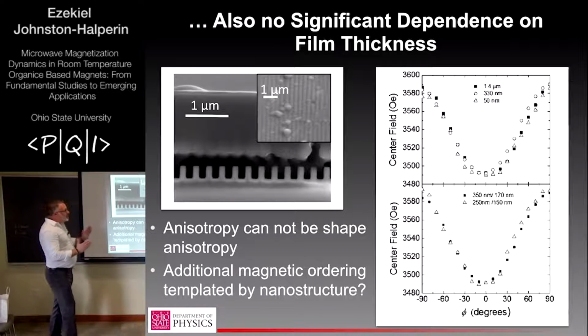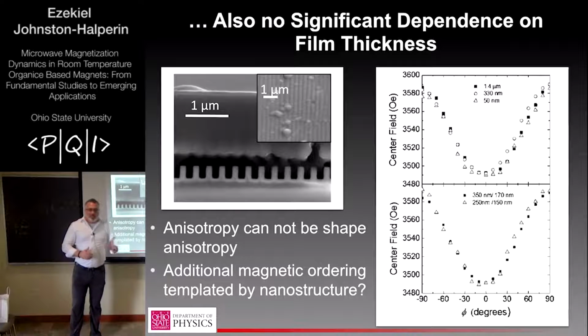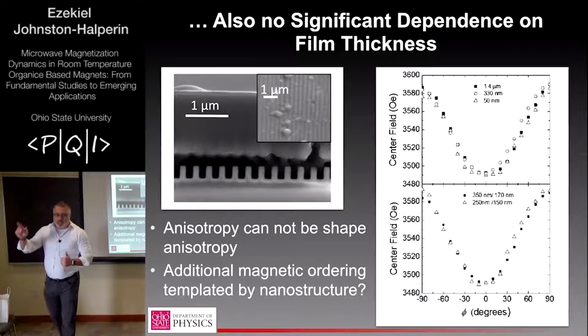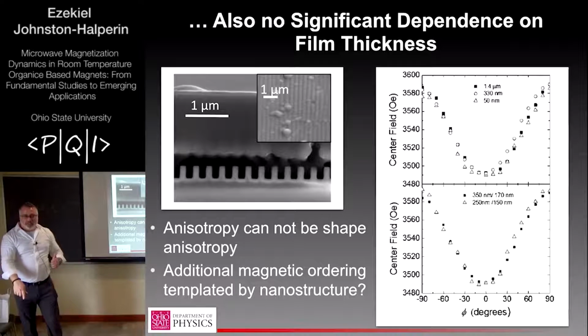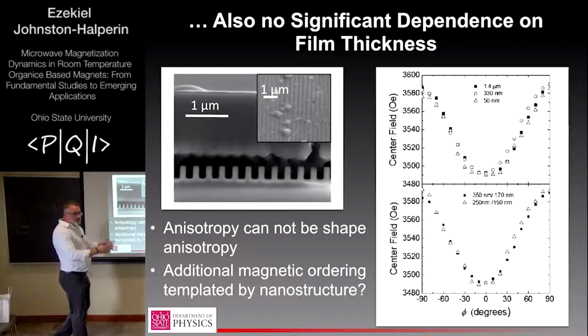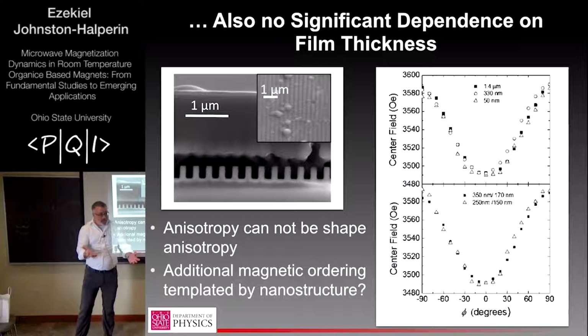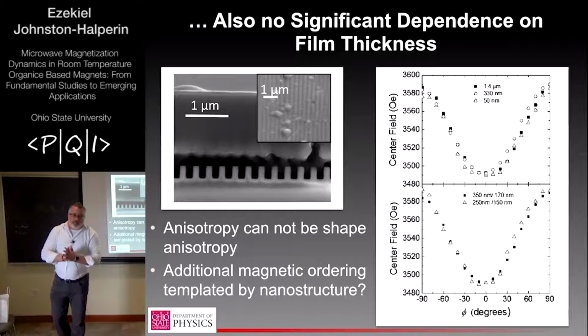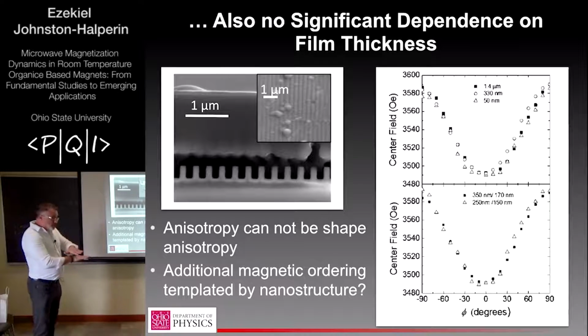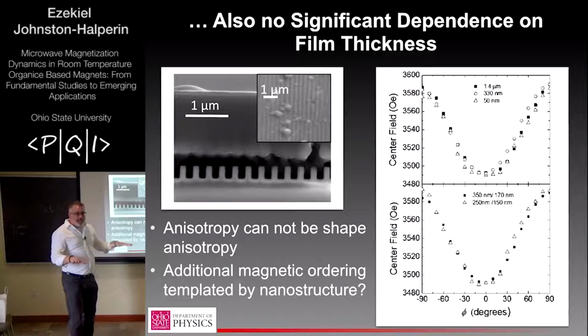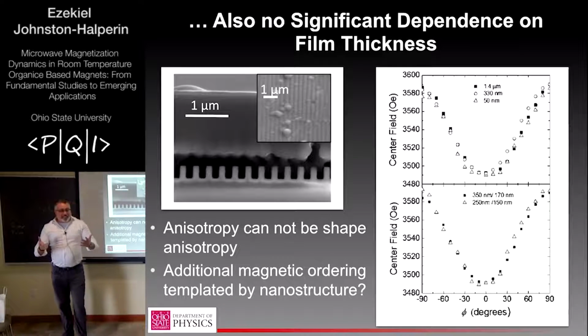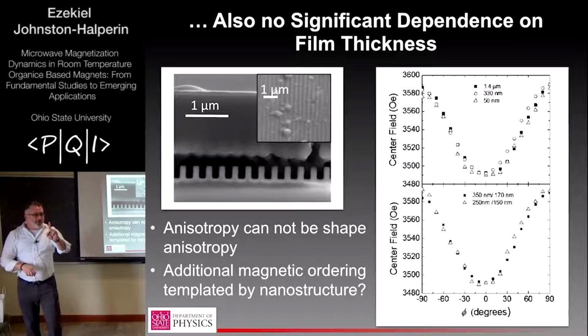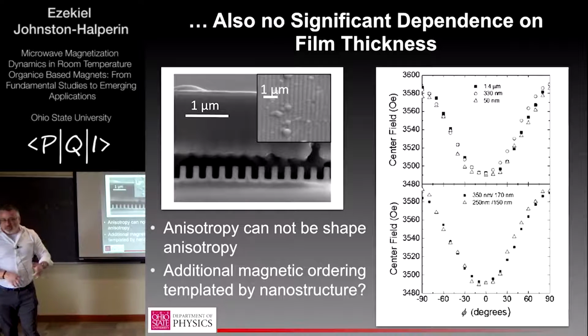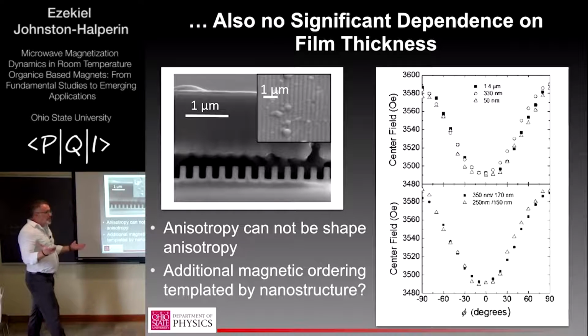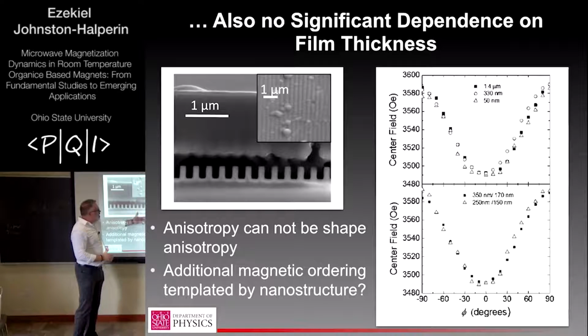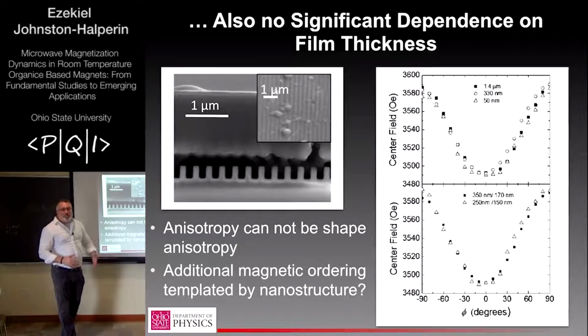And so retroactively, coming back to the data I showed you at the very beginning of the talk, we can measure in-plane to out-of-plane anisotropy in thin films, which we assumed was just a shape effect. And I think that's there, that's part of it. But as part of that, we suspect there's also some surface templated anisotropy there as well. It just happens to be pointed in exactly the same direction as the shape anisotropy, so we had no idea it was there. So this is sort of giving us a lot of interesting food for thought.